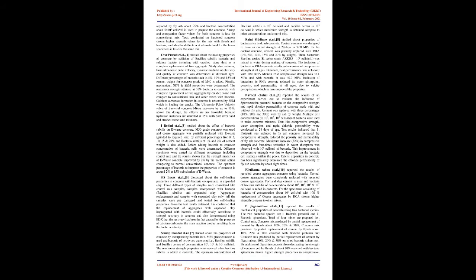The maximum strength was attained at 10% bacteria in concrete with complete replacement of fine aggregate by crushed stone dust, compared to the conventional mix and other mixes with bacteria. Calcium carbonate formation in concrete is observed by SEM, which is healing the cracks. The ultrasonic pulse velocity value of bacterial concrete mixes increases by up to 10%. Above this dosage, the effects are not favorable because hydration materials are saturated at 15% with both river sand and crushed stone sand mixtures.